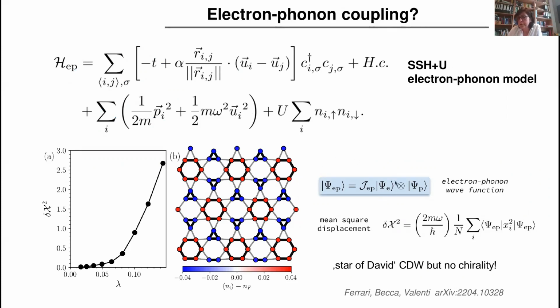We have to extend the wave function by including not only the electronic part, but also the phononic part. By including the phonons, letting the distortions of the lattice act as phonons in this material, the kind of distortion the system favors is a Star of David charge density wave, but without chirality.